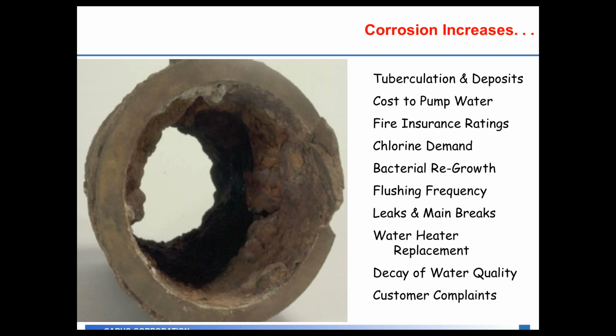As that pipe becomes restricted and no longer a smooth surface, it costs you more to pump the same amount of water through that pipe in the distribution system, because now the restriction is impacting your pumps. If those pipes get so bad that it influences the flow rate out in the distribution system, one of the things the fire department does is do flow rates on the fire hydrants. In those cases, that's actually setting the fire insurance rating for homeowners and the community itself. If they can't get sufficient flow velocity out of the hydrants, that increases the cost of insurance to homeowners in that municipality.